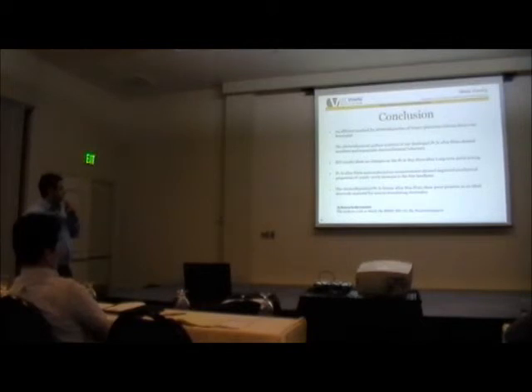The conclusion includes: all goals were met. An efficient method of deposition was developed. Electrochemical surface analysis of the surface showed excellent results. EIS results showed no changes after 60 days, which is perfect. And this alloy's nano-indentation measurement showed 100% improvement in its mechanical properties. This platinum iridium alloy is a good promise and an ideal electrode material for neural stimulation electrodes.